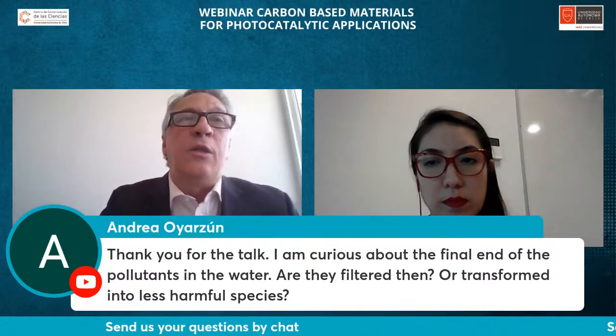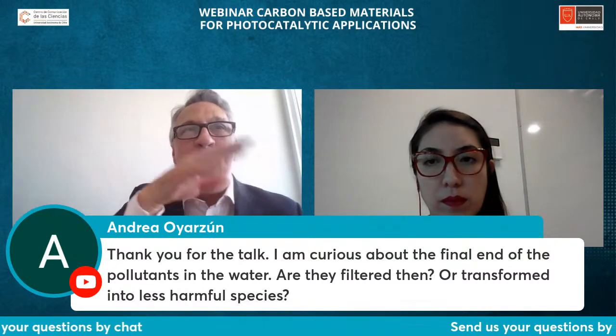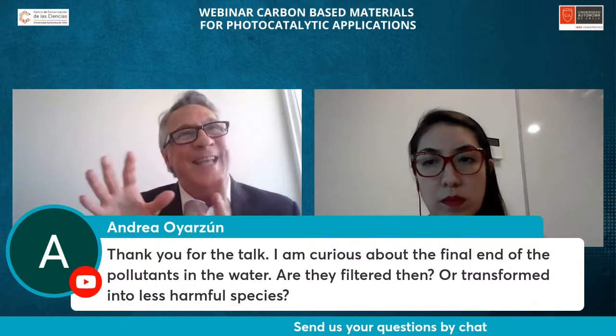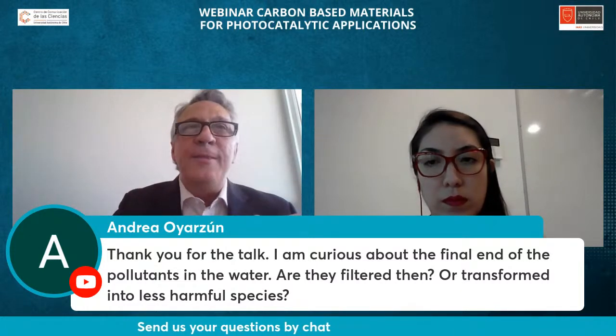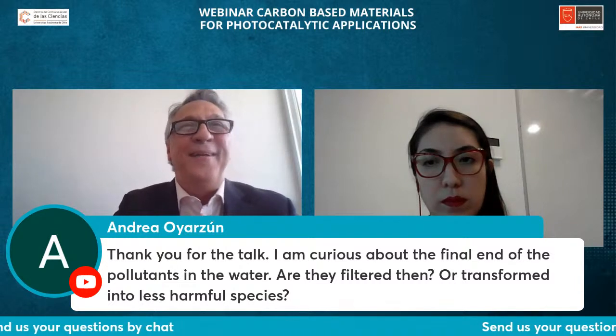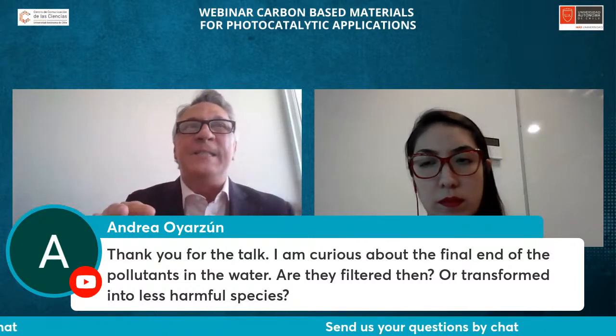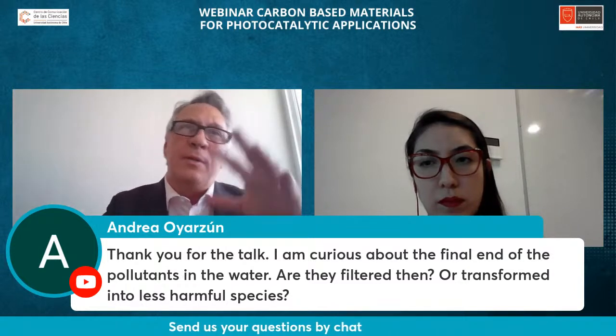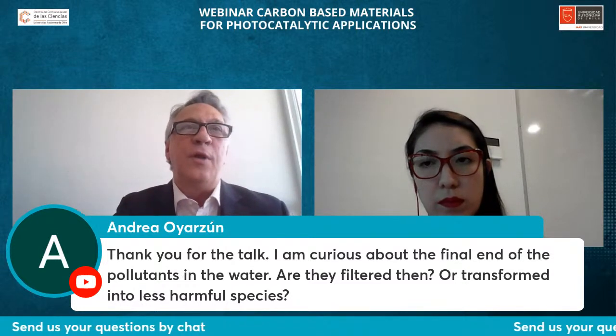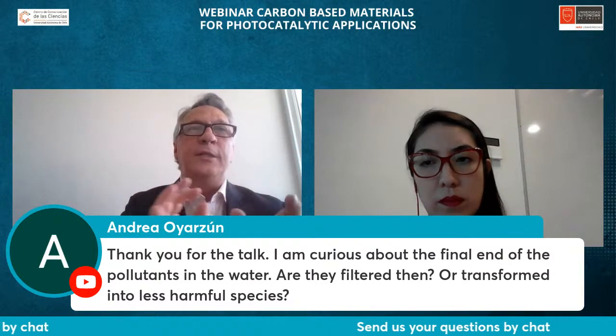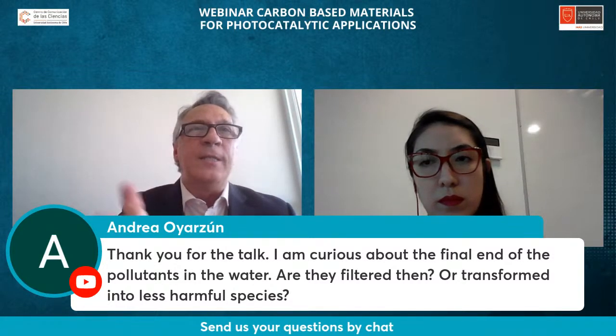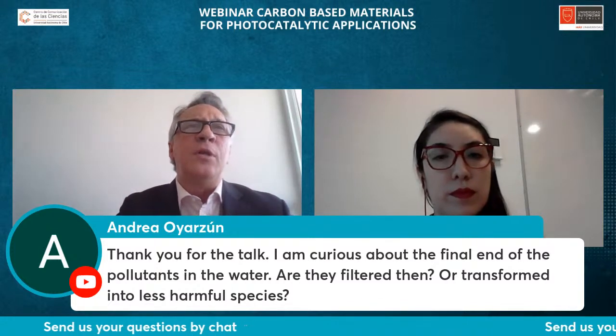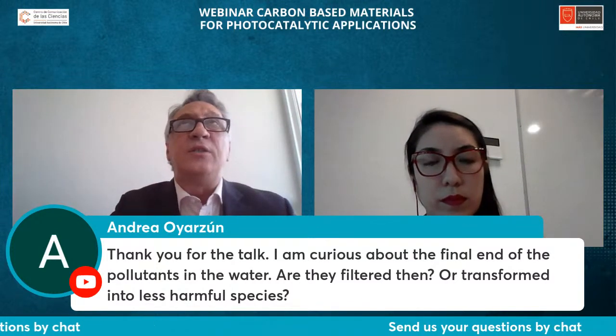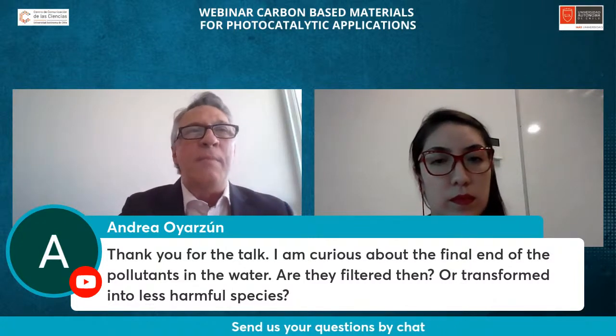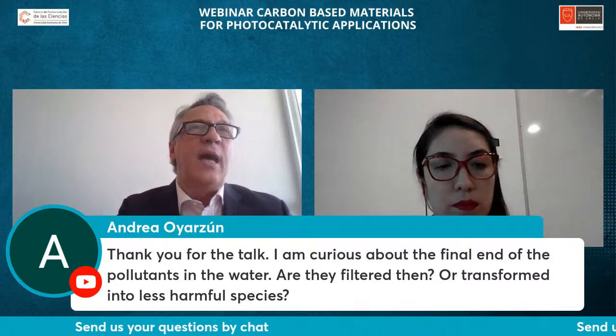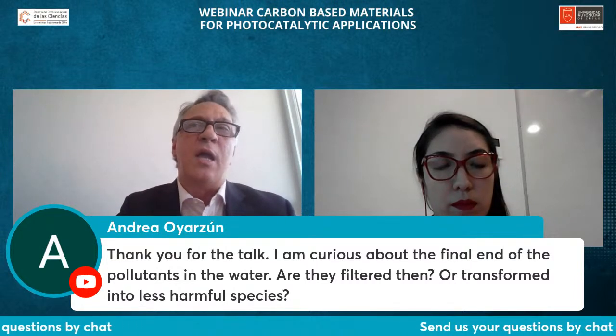The only thing you need to filter, after you have already depolluted all the pollutants and the intermediates, is the catalyst. In this case, it's also much better to work with carbon than with titanium dioxide, because it's easier to filter carbon than titanium dioxide. Well, depending on the size of the carbon. If you are dealing with graphene that is very well dispersed, you need a very interesting filtration system. But that is not the case. Commonly, we introduce nanoporous carbons with an average particle size of 18 to 100 micrometers, so it's very easy to filter that kind of material.